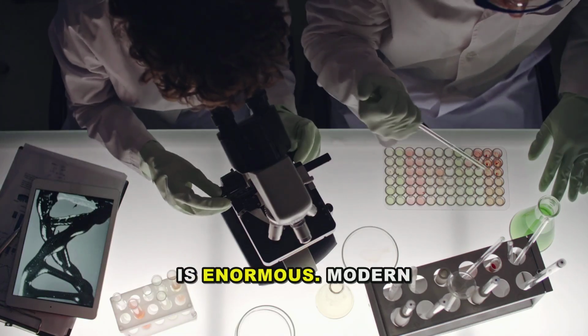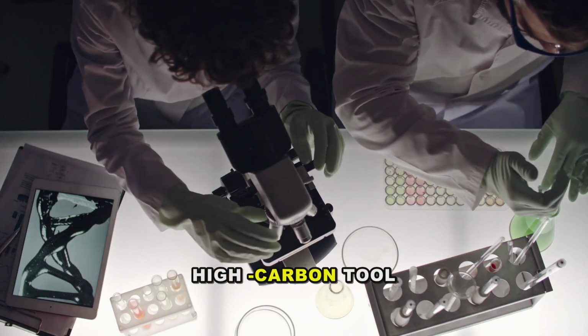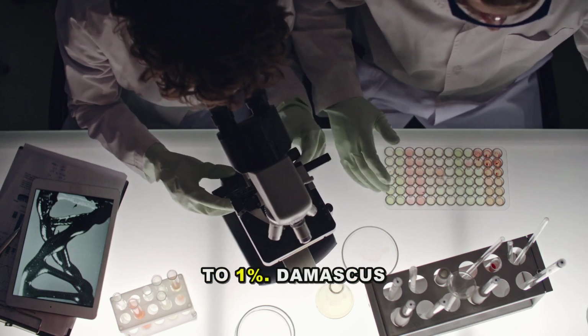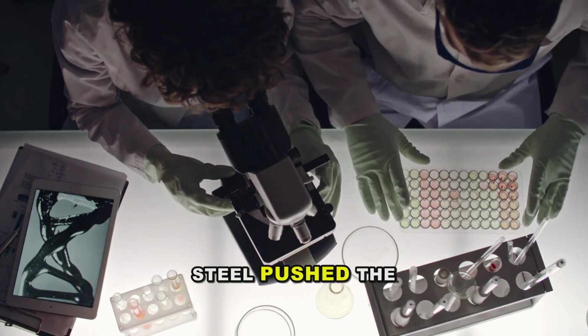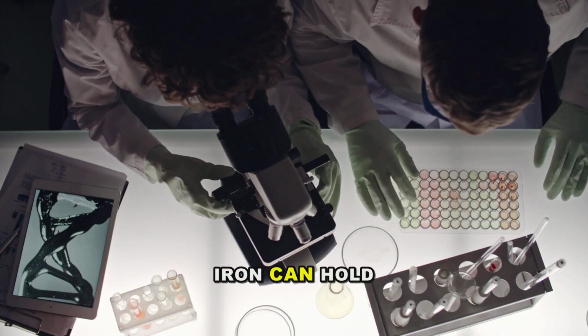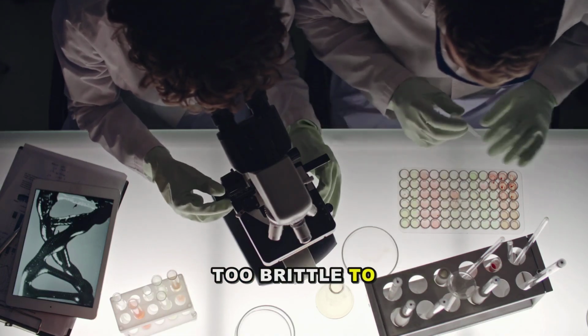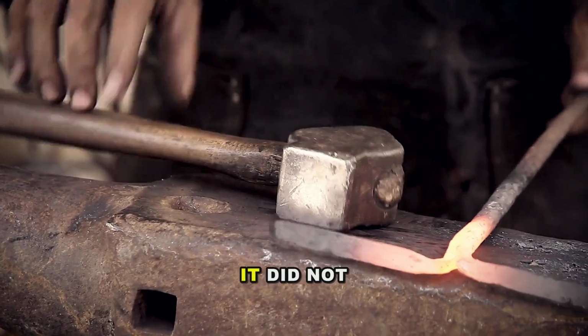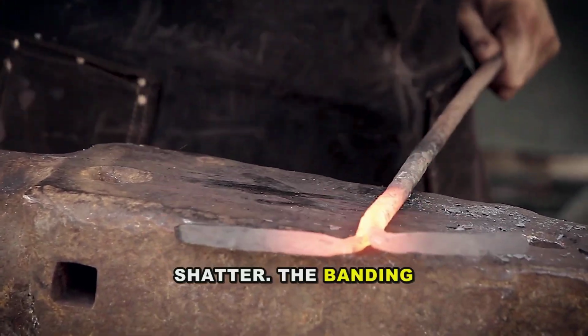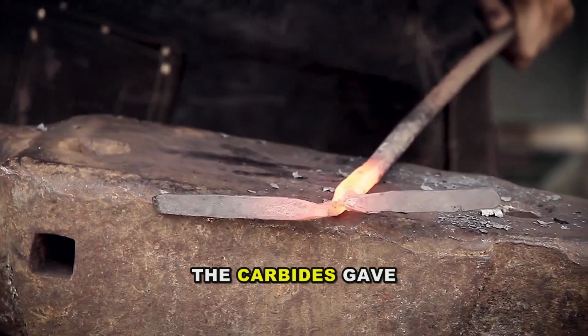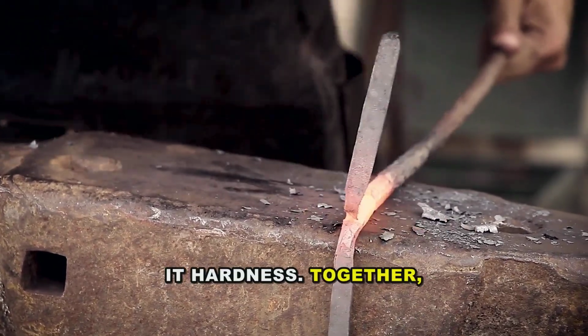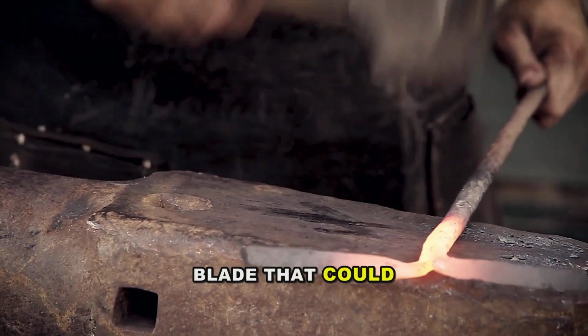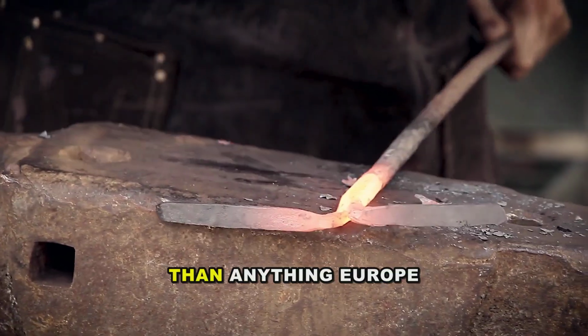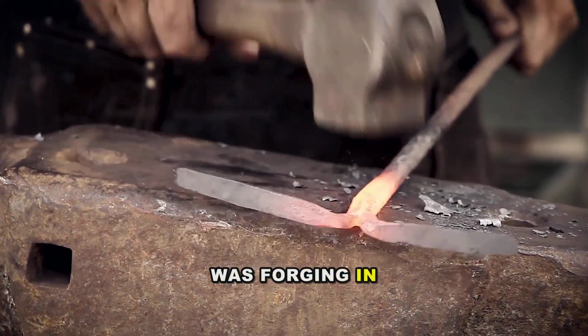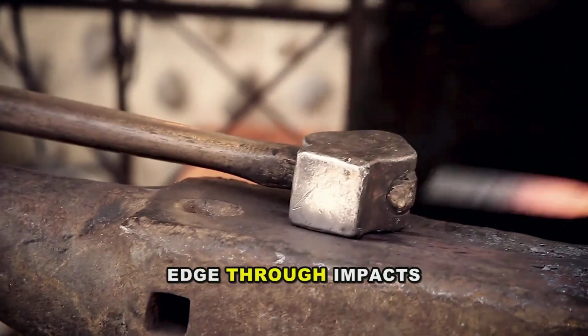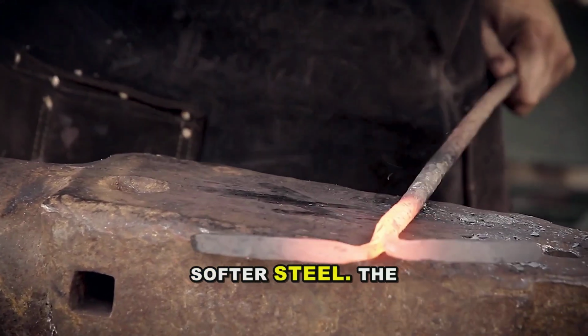That is enormous. Modern high-carbon tool steel sits closer to 1%. Damascus steel pushed the metal to the edge of what iron can hold before it becomes too brittle to forge. And yet, it did not shatter. The banding gave it flexibility. The carbides gave it hardness. Together, they produced a blade that could be sharpened to a keener edge than anything Europe was forging in the same era and keep that edge through impacts that would ruin softer steel.